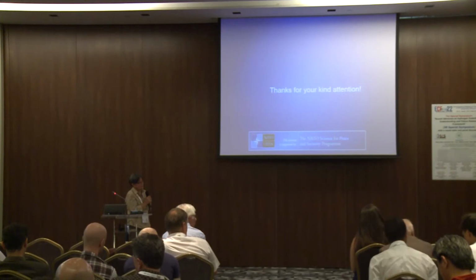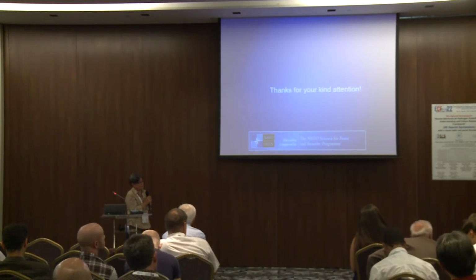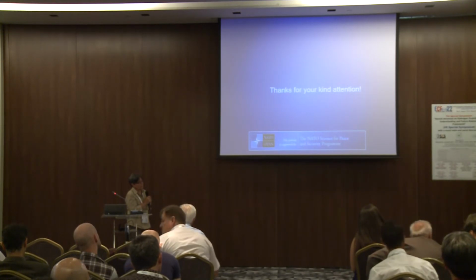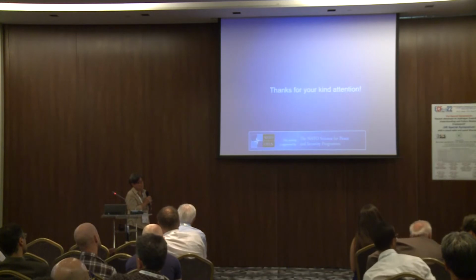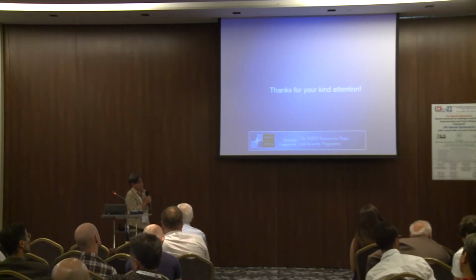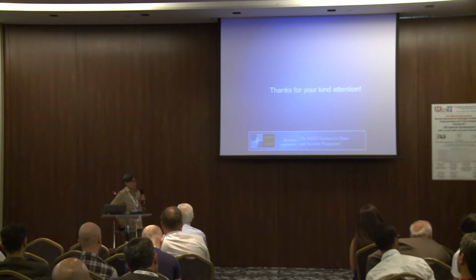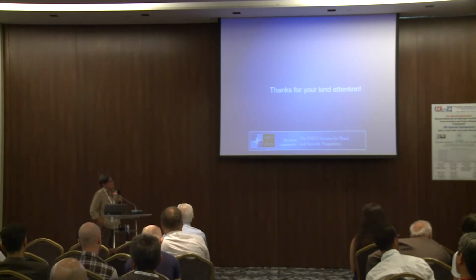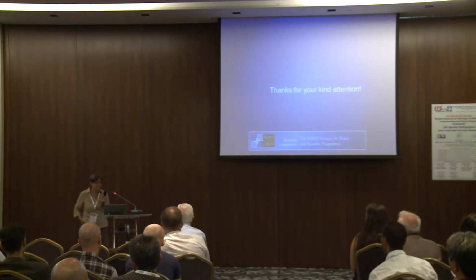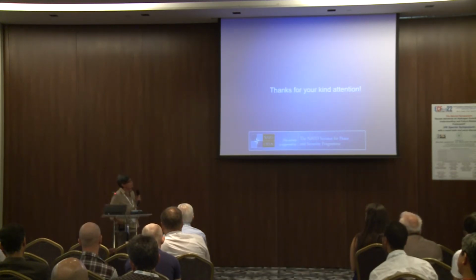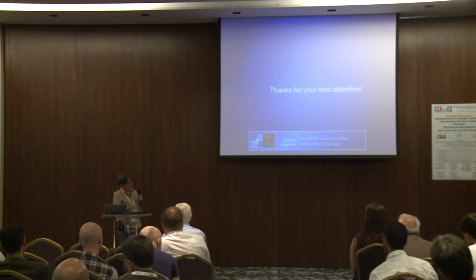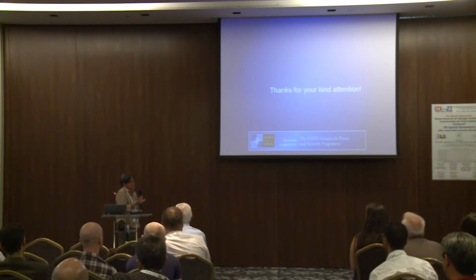From your point of view, what are the most critical micromechanical properties which we should measure during overhaul, during maintenance, in order to reveal the true effect of hydrogen in such type of steels and this particular application? No, in this case, we are not going to reveal the source of the damaging. So we are just going to reveal with a very fast non-destructive technique that something is going on in the material. Therefore, what is the reason for something going on in the bulk material properties? The reasons behind that will require deeper investigation.